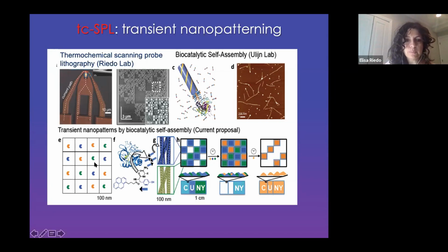So the idea here is to pattern enzyme on a surface with tc-SPL, where ideally we can have 1 enzyme per spot, and then bring in a solution with these peptides, the biofuel, and start the growth of the fibers in each spot. And if we can also pattern different enzymes, we will have also different types of fibers. So what it shows here is that depending on the biofuel, we can activate the fibers green and blue, or we can activate the fiber orange, green, and blue, or only the fiber orange. So we can control in time what nanostructures form. So this is the general idea.